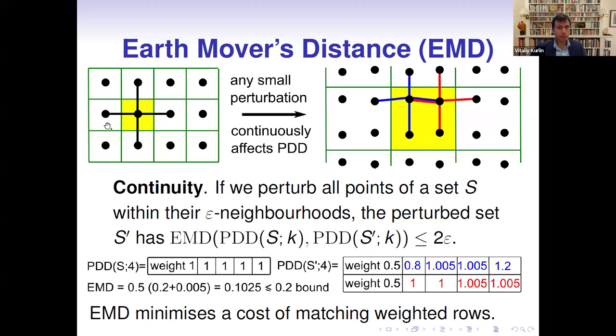Under small perturbation, that square lattice might get a larger cell, four times larger in this particular example. And since I symmetrically perturbed the points here, so I shifted up by 0.1 this point and pushed down this point also by 0.1, then this larger unit cell has an asymmetric unit consisting of two points, so these two points, with blue and red edges, exactly form an asymmetric unit of four points, so on the two of them.